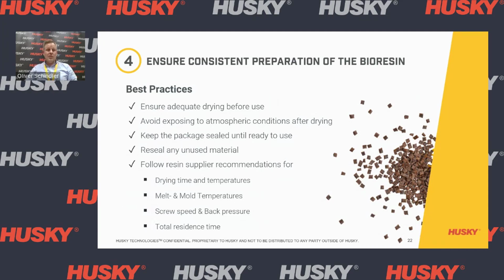So it's very important to follow resin supplier recommendations for drying, melt temperatures, mold temperatures as well, the screw speed and the back pressures, as well as the total residence time. And here the most challenging point we see is that often suppliers and molders tend to increase the temperatures to fill the cavities more easily because they are seeing very high pressure drops. And then the material suddenly burns. So you are always in between capabilities, and you should ensure to really stay within the supplier recommended values here.